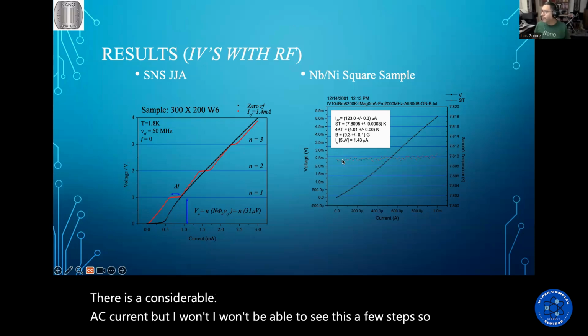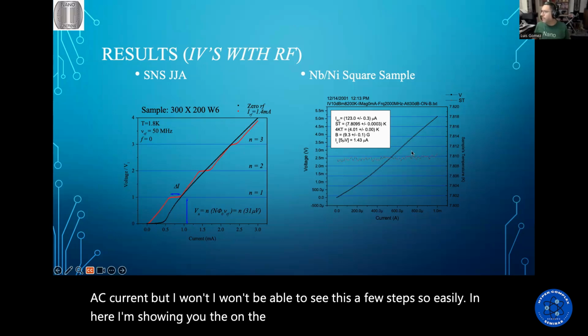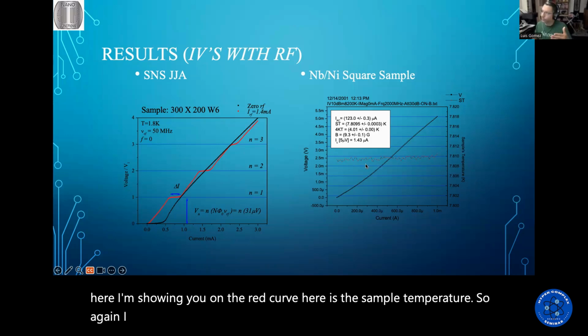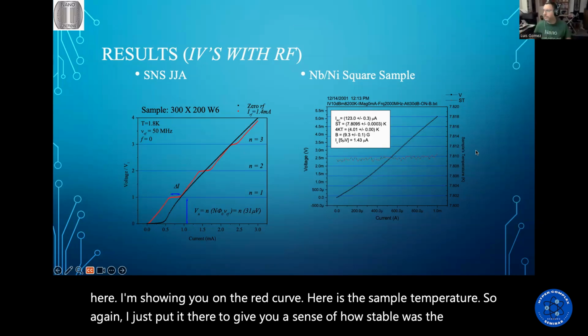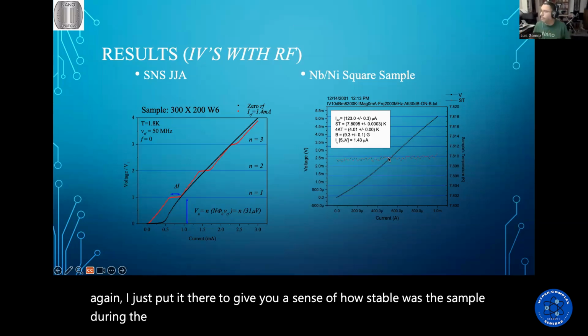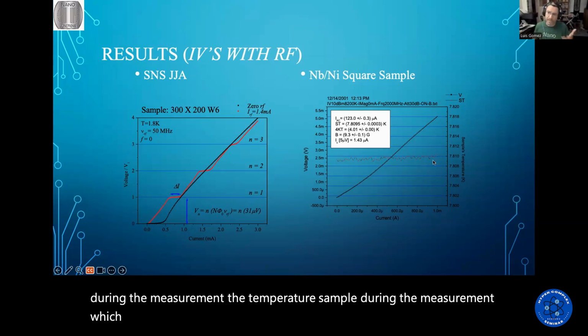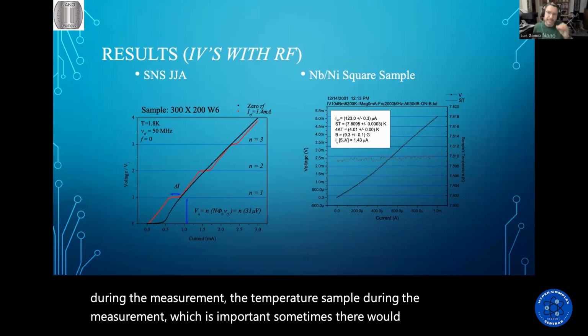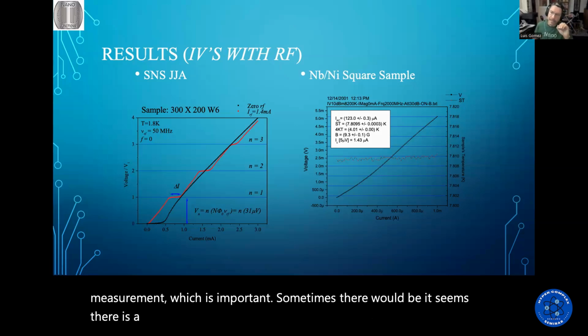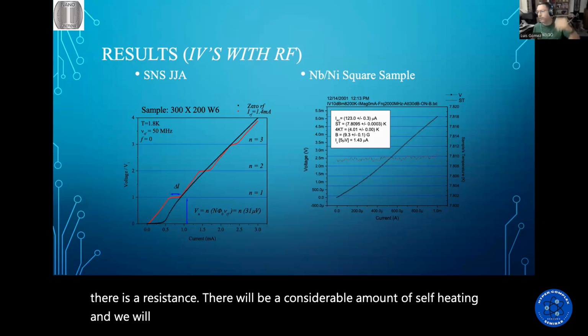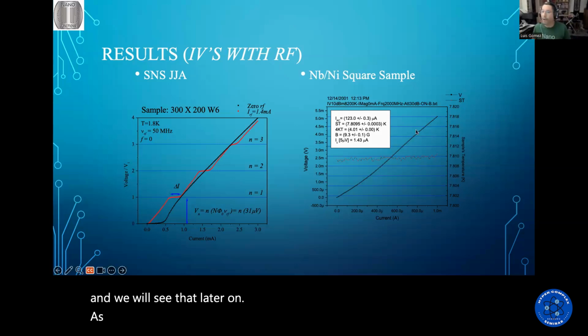Here, the red curve shows the sample temperature - I just put it there to give you a sense of how stable the sample was during the measurement, which is important sometimes. There would be, since there is a resistance, a considerable amount of self-heating, which we will see later on as we increase the power of the RF signal we're applying.